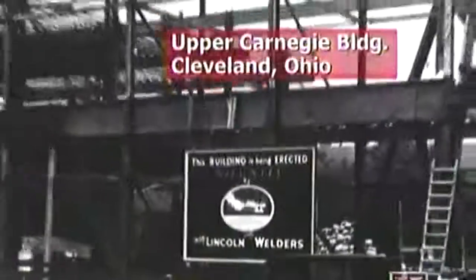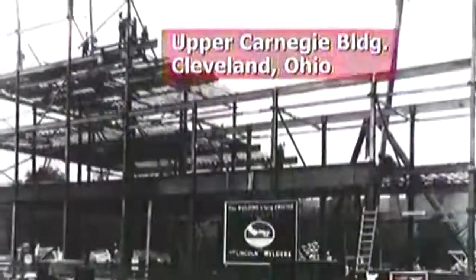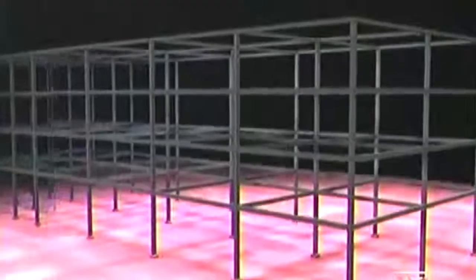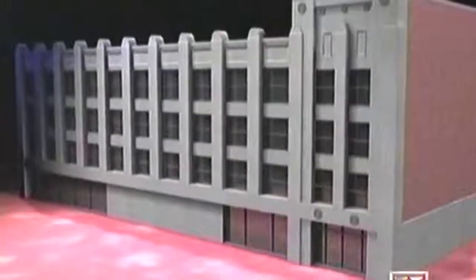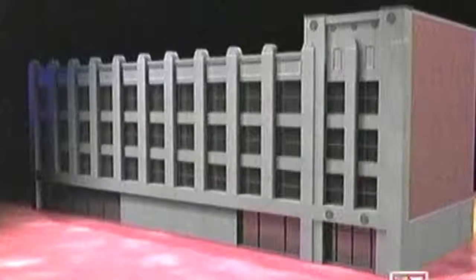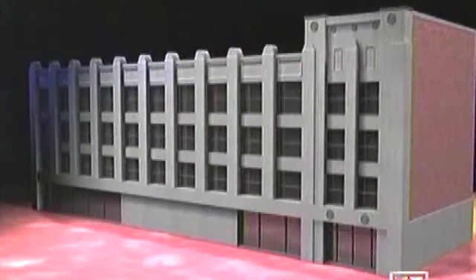In 1928, Lincoln Electric joined with a local architectural firm to erect the first commercial building wholly constructed from arc-welded steel. In the Upper Carnegie Building, the typical dense network of riveted steel was replaced by a series of continuously welded beams that ran the entire length and height of the building. Not only did welding free up space, but these continuous beams carried even greater loads and stresses than their riveted counterparts. Connections are always the weak point in a structure.